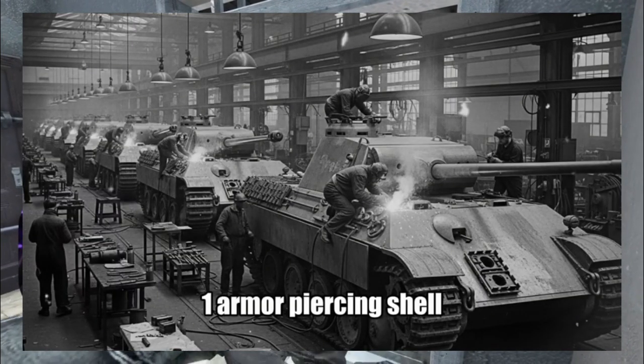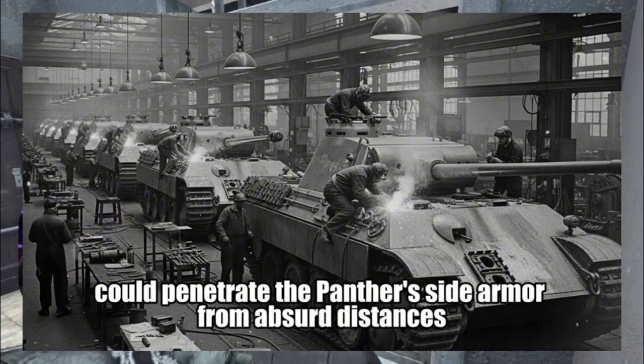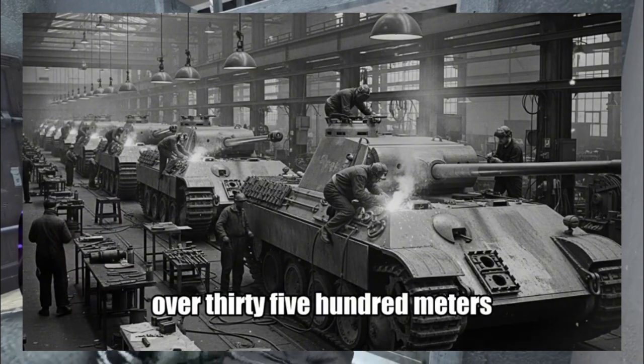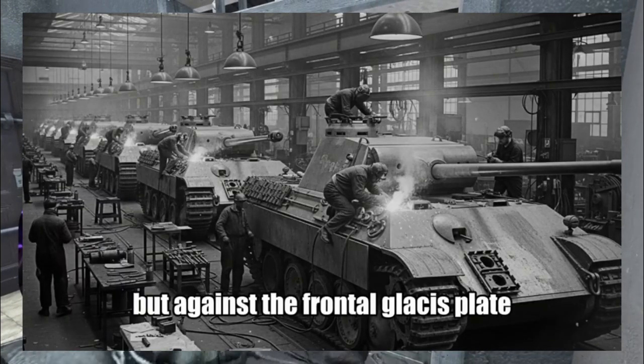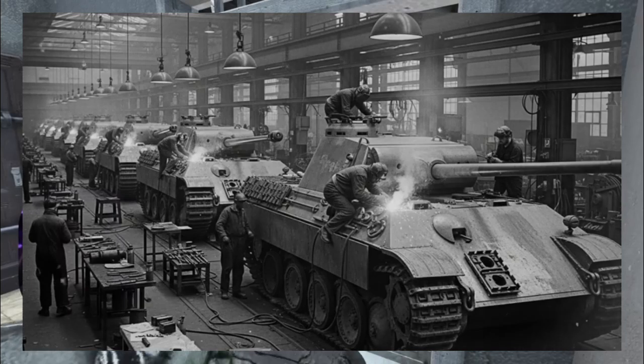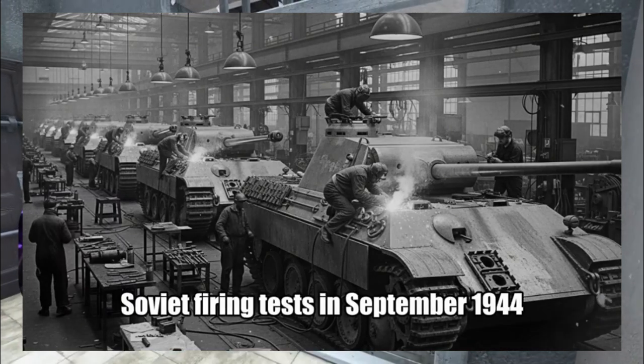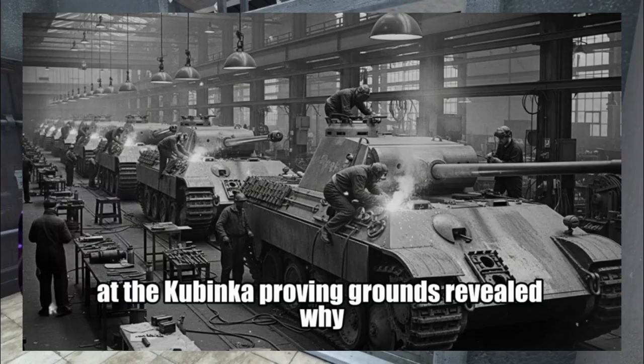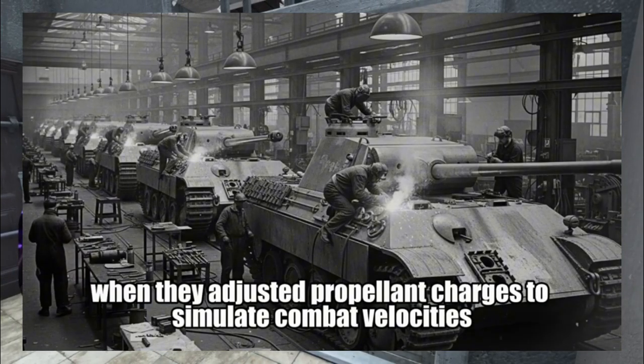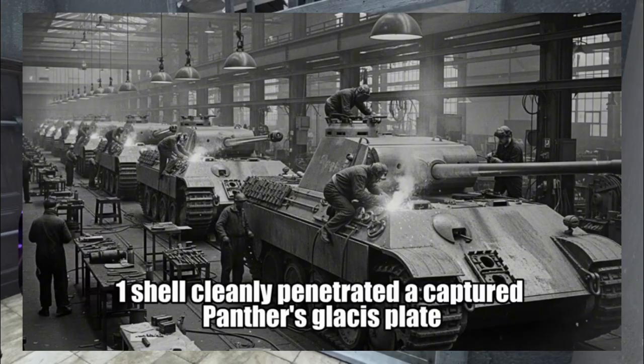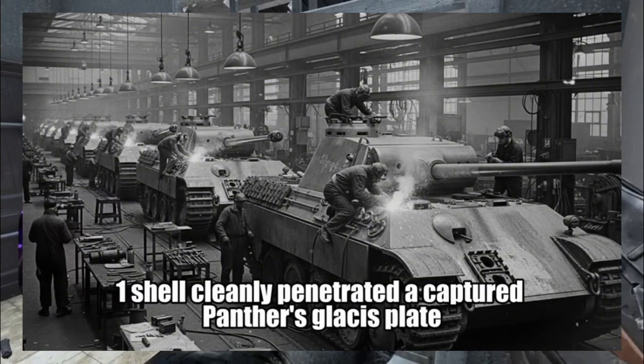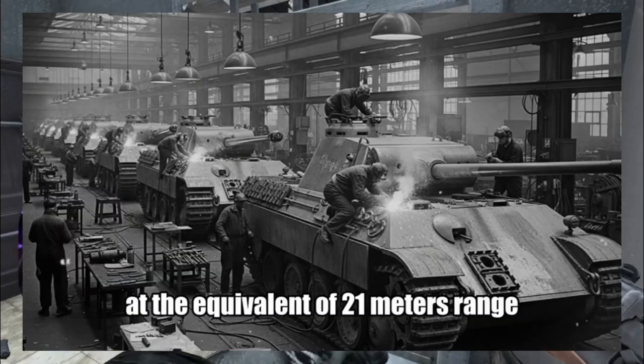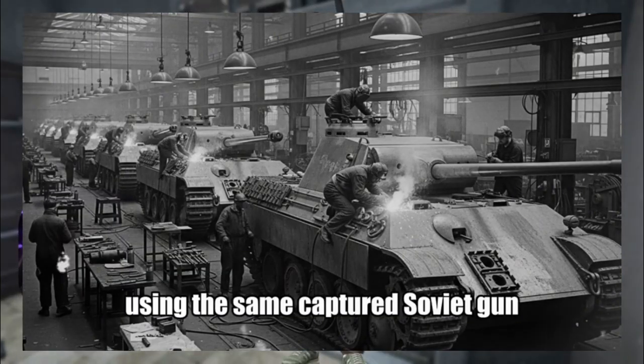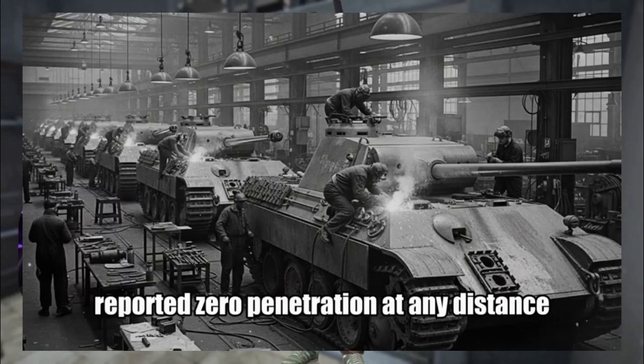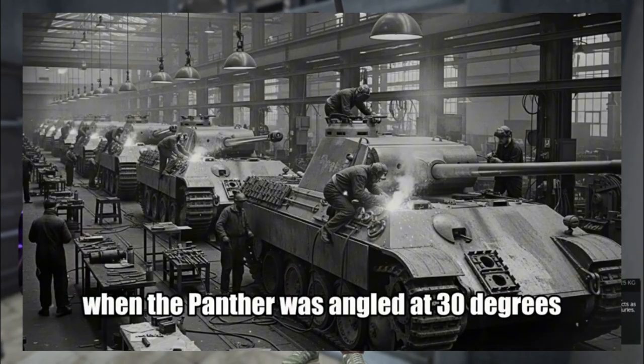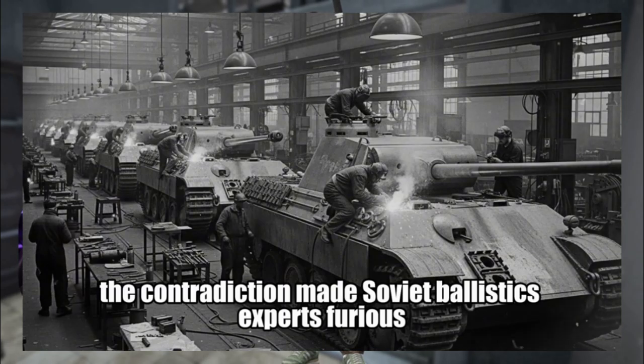The BR-471 armor-piercing shell could penetrate the Panther's side armor from absurd distances, over 3,500 meters. But against the frontal glacis plate, results were maddeningly unpredictable. Soviet firing tests in September 1944 at the Kubinka Proving Grounds revealed why. When they adjusted propellant charges to simulate combat velocities, a BR-471 shell cleanly penetrated a captured Panther's glacis plate at the equivalent of 2,100 meters range. Yet German tests using the same captured Soviet gun reported zero penetration at any distance when the Panther was angled at 30 degrees. The contradiction made Soviet ballistics experts furious.